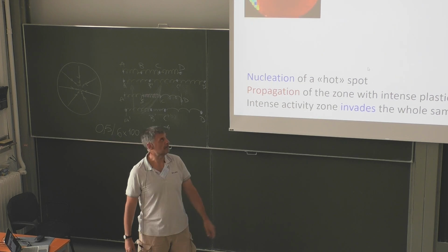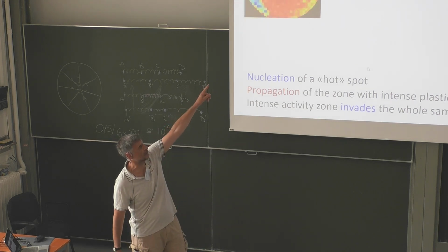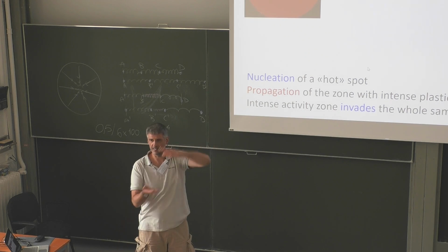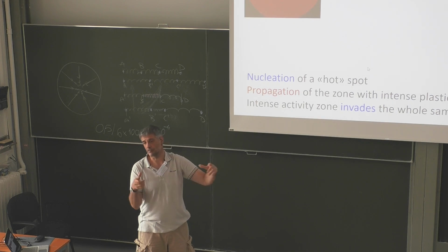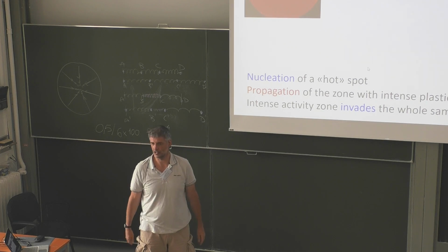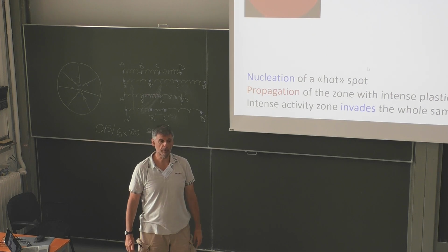Right. The fact that everything starts from the boundary should not be a big surprise, because this is a plate-plate geometry, and the stress and the strain are larger at the rim of your plate. This is different from cone-plate geometry. It could happen close to a plate. I'm sorry? It could happen near one of the plates. You don't know. It could.